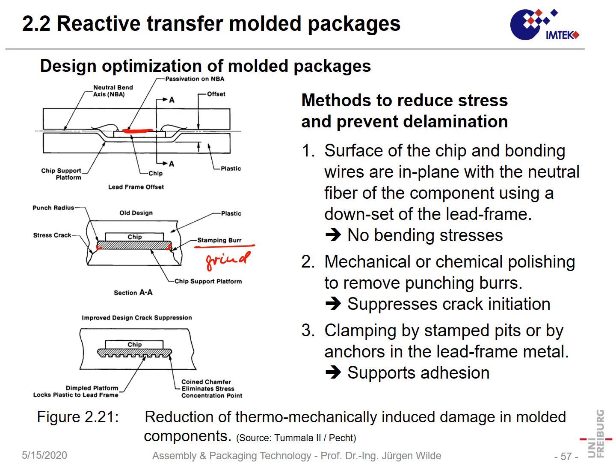Another effect which is important is, when we look at stresses, we must say such an assembly is always unsymmetric. That means it is like a bending structure, and that always means on the convex side we have tensile stress, and on the concave side we have compressive stress. And that would mean we can have stress in the chip surface. By having this depression in the lead frame before we mount the chip, we can control our package in a way that the top side of the chip is in the neutral bend of this package.